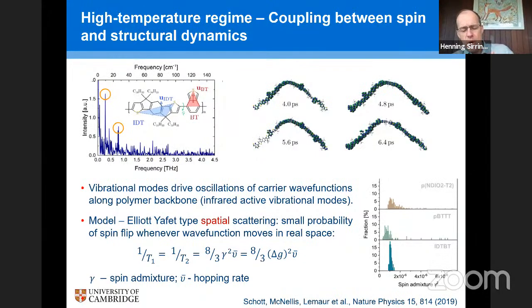It's a mechanism that's probably similar to what's called the Elliott-Yafet mechanism for spin relaxation, where normally people think of that in momentum space: Bloch electrons with particular wave vectors scatter at defects and change their wave vector, and there is always a small probability that when this happens, the spin of the electron flips. That's the so-called Elliott-Yafet spin relaxation mechanism that's very well studied in inorganic semiconductors. And we think that in these organic systems, we have a very similar mechanism, but not in momentum space, but in real space: as the wave function of the electron oscillates rapidly along the backbone, driven by these structural vibrations, there is a small chance every time it oscillates that the spin will flip.